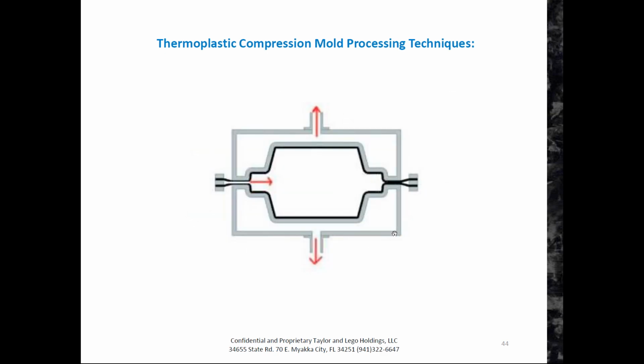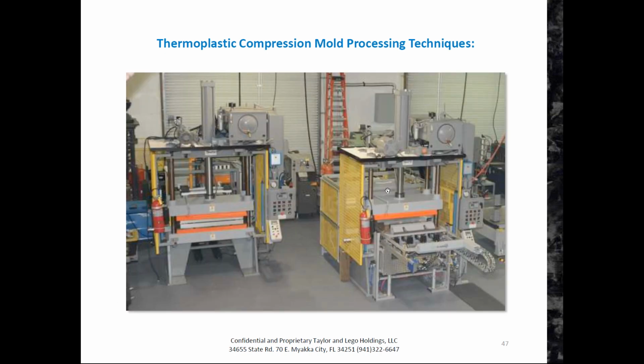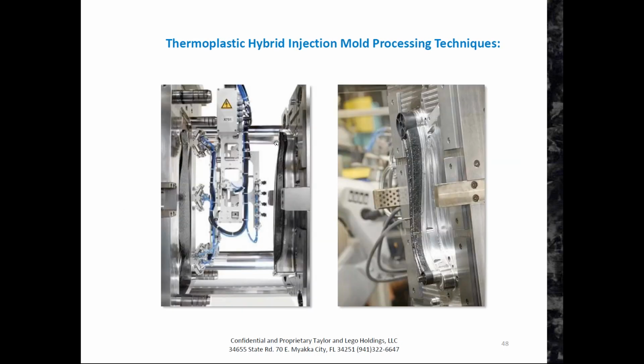There's a whole bunch of different processes described in here, and I'll just blow through this really quick. These are 2 of our presses. They're not our only presses, but these are 2 of our presses that are vertical. This system right here is about a $750,000 system, and it actually can mold large parts with undercuts. Both of these presses are 12.5 feet tall. There's another thermoplastic process behind the one that does continuous pre-consolidated sheets that wants to be a continuous thickness.